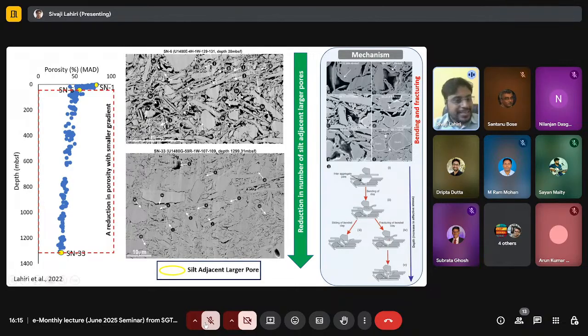Now, in the sample SN6, we dominantly observe this kind of silt adjacent larger pores. However, in the sample SN33, this kind of silt adjacent larger pores are almost missing. Now, based on this observation, we can conclude that reduction in number of silt adjacent larger pores caused reduction in porosity from 30 meter to 1300 meter depth.